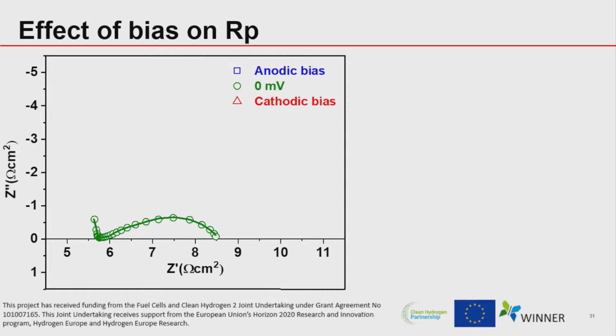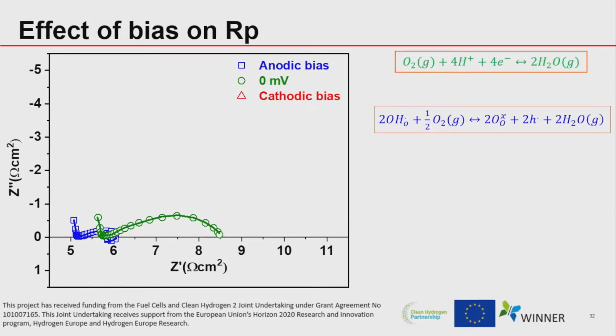But I had no idea what is happening in anodic bias or cathodic bias, or what if I expose these materials to high cathodic or anodic biases. But now I'm trying to understand what happens when I apply bias. If I apply anodic bias, what I see is that the R ohmic has decreased and the RP has also decreased. Decreasing in the RP is very obvious, but what leads to decrease in R ohmic?